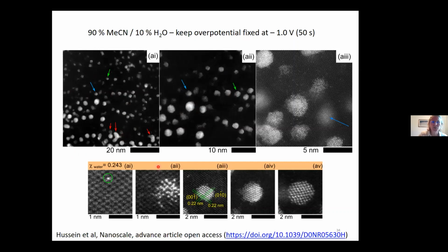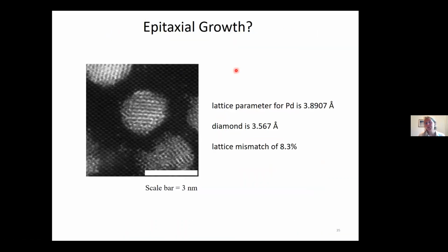But also in the background of all of this, when we zoom in, we've still got single atoms and we've still got atom clusters, but they're very much in the minority. What we're seeing under this length scale is these beautiful nanoparticles emerging. And actually, when you go and look at these high resolution ones, remember the boron doped diamond, because as I said, by the time we've polished it, it's majority 110.